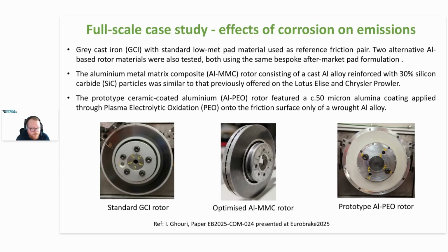Firstly, a prototype aluminium metal matrix composite rotor, as previously fitted to the Lotus Elise and Chrysler Prowler. And secondly, a plain aluminium disc alloy coated with a alumina ceramic surface layer, as applied by plasma electrolytic oxidation. The two aluminium discs both used bespoke aftermarket brake pads supplied for the Lotus Elise, whereas the grey cast iron used a standard low-met brake pad.